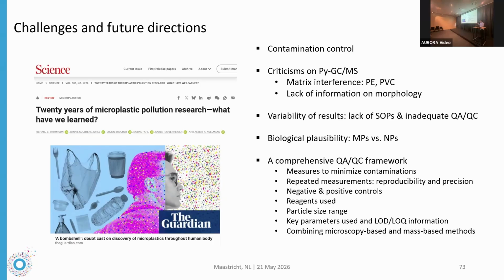And recent effort has been made to propose a QC framework for micro-nanoplastic exposure assessment relevant to human exposure, partially building upon established QC frameworks for environmental samples, highlighting some key aspects. For example, measures to minimize contamination, and repeated measurement to enhance reproducibility and precision. And as I also mentioned, negative controls and positive controls should be set. And also we need to be transparent about the reagents, including solvent, surfactant, and digestion chemicals that we use, and also the concentration, and maybe also under which condition they were used.